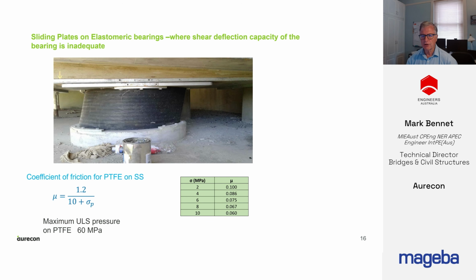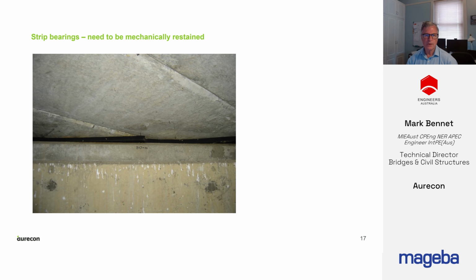If the shear capacity of your elastomeric bearing is too small, you can incorporate a sliding plate interface on the top of the elastomeric bearing. The thing to note with this approach is that the coefficient of friction of sliding surfaces is pressure dependent, and that the pressure allowed on sliding pads is a lot higher than the pressure allowed on elastomeric bearings. So to get a low coefficient of friction, you should make your sliding pad quite a bit smaller than the elastomeric bearing. Strip bearings are invariably placed on an incline, so should be mechanically restrained.